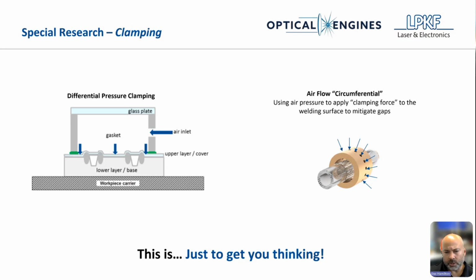It's a little bit hard to see here in the picture on the right, where you have a thinner outer film, and then maybe a tubing substrate. And this ring here is radially drilled, and it's acting like a manifold with air pressure so that you can actually get air pressure circumferentially. So similar to the differential pressure clamping, but in a radial format. And again, this is just to open your mind to what some of the possibilities are and get you thinking about different ways to clamp.